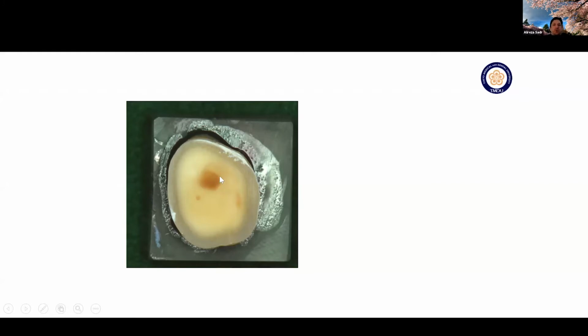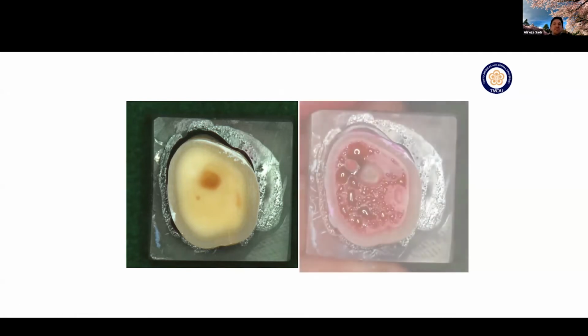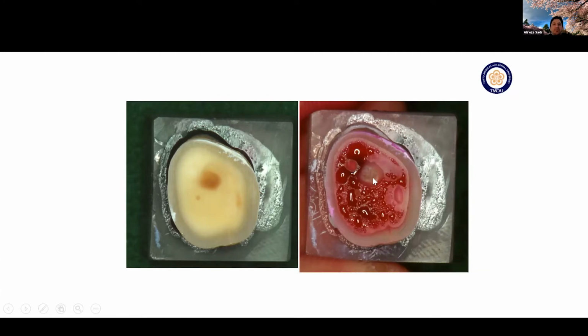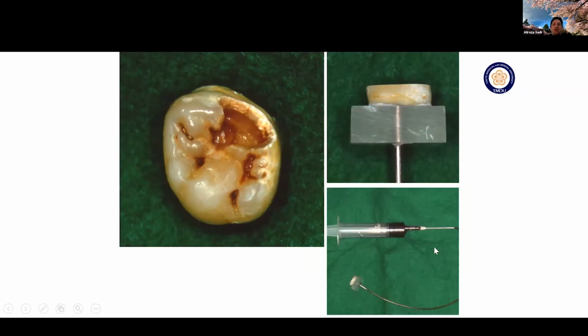So what Tagami showed in this slide is striking, showing that if you have caries affected dentin, which is showing a lower permeability than sound dentin because of the precipitation of minerals as a result of continued de and remineralization, then you have actually less permeability, right? Less permeability. So he is injecting the dye here from the pulpal side and looking at filtration of the solution through the pulp.